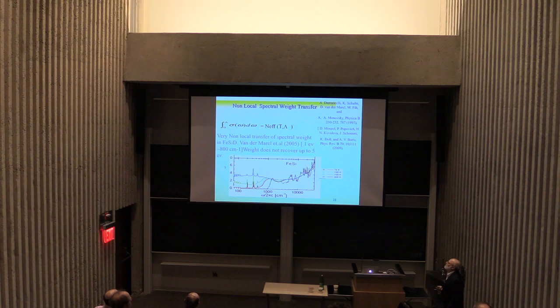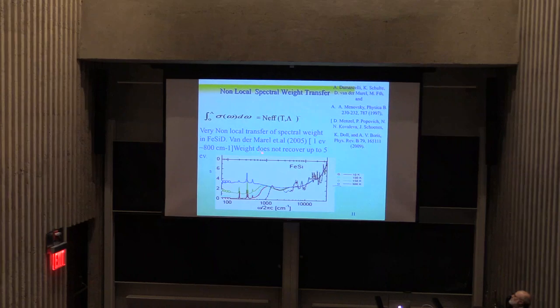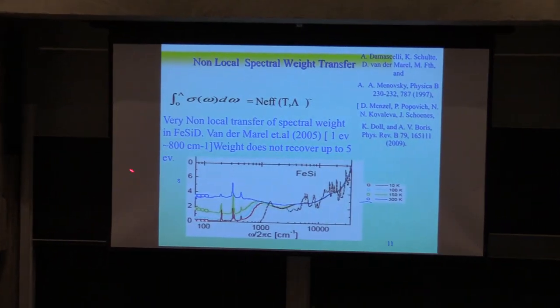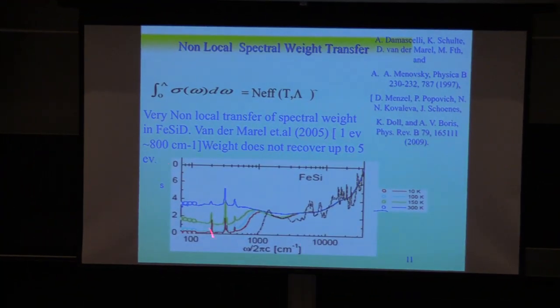So let me give you some examples that indeed, besides high temperature superconductivity, correlated materials really do extraordinary things. Just one example of something that I always found striking is the violation of low energy sum rules. There's a sum rule in solid state physics that says that if you measure the optical absorption of the material, and if you integrate it up to infinity, that thing has to be a constant. Now, here we're integrating it up to some high energy scale, and we call that the effective number of carriers. So in weakly correlated materials, this depends very weakly on temperature. In strongly correlated materials, that's not true.